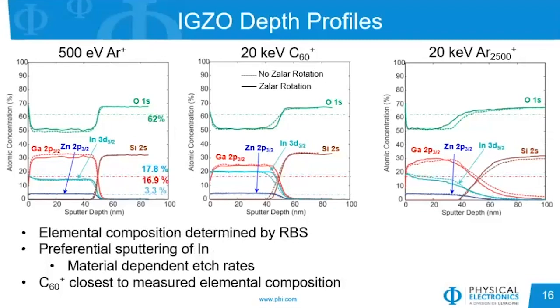We can also look at things like preferential sputtering with these different types of guns. When you have multi-component samples like this, the sputter rate of each of the components can be slightly different, and so your overall stoichiometry for the material may not be quite accurate to what your expected values are. So if we look at the start on the monoatomic argon on the left, we can see that the indium concentration is slightly below the 17.8 that we would expect from RBS analysis of this material. For the C60, it is slightly higher than the expected value.